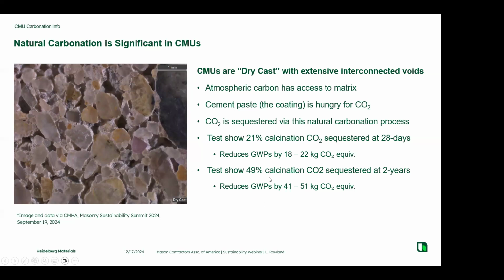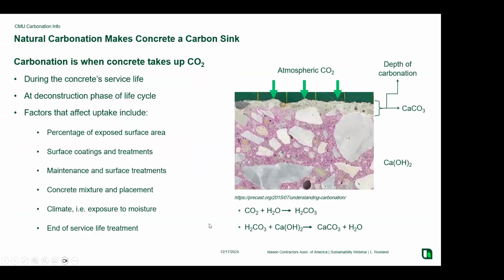calcination process. Tests show that 21% of all the calcination CO2 associated with a cement manufacturer that happens in the production of all the materials that go into your block, within 28 days, 21% of that CO2 is reabsorbed. So it reduces your GWP by 18 to 22 kg per cubic meter. Within 2 years, 49% of all that calcination emissions are sequestered and picked up. And of course, you have a much higher reduction in your GWP because you've reabsorbed that CO2. That natural carbonation is a huge carbon sink in the system. Thank you to the CMHA for these images and this information.